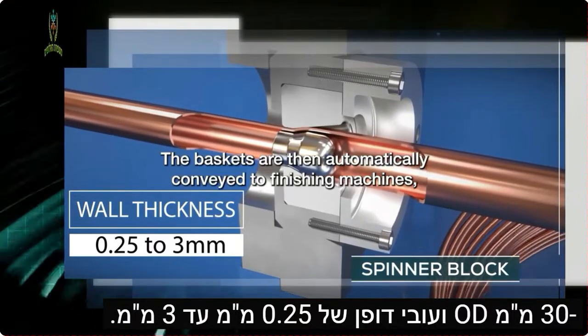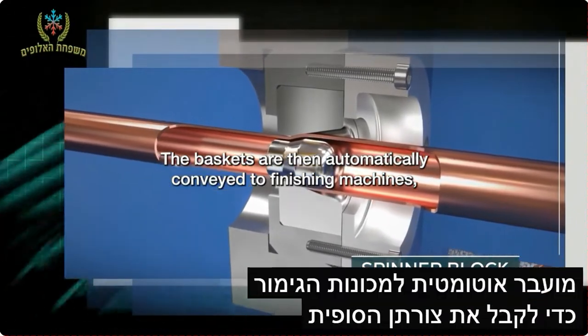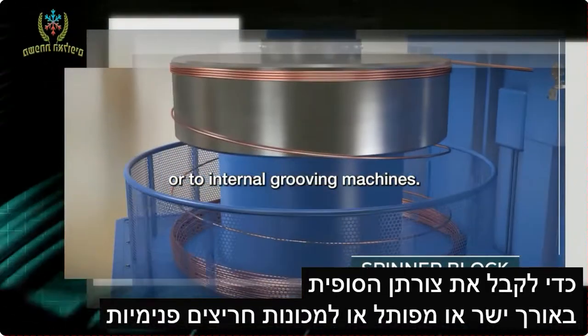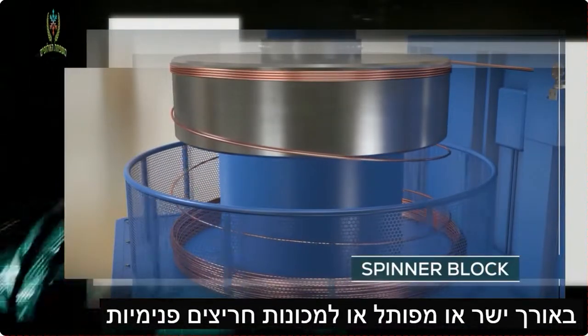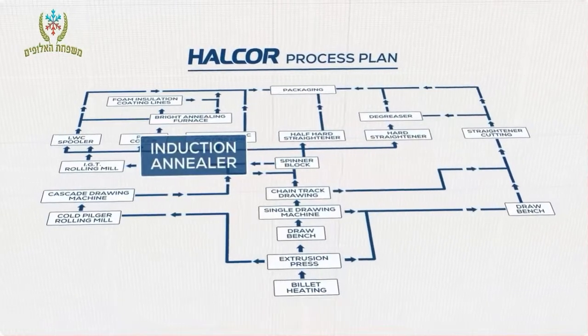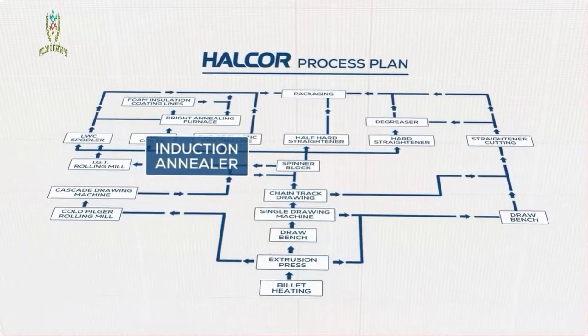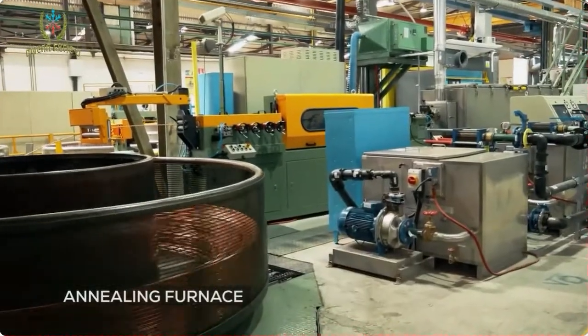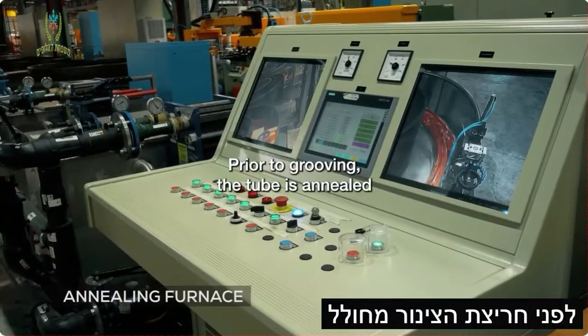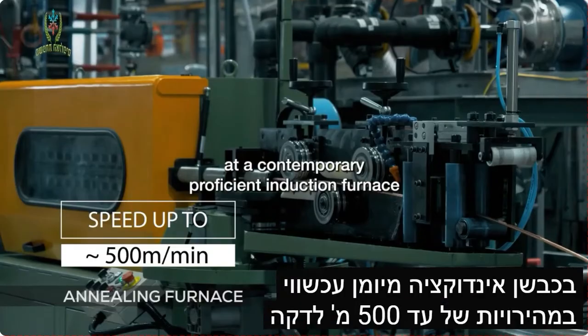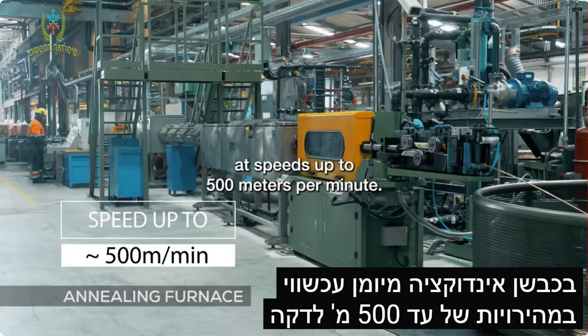The baskets are then automatically conveyed to finishing machines, to get their final form, straight length or coiled, or to internal grooving machines. Prior to grooving, the tube is annealed in a contemporary, highly efficient induction furnace, at speeds up to 500 meters per minute.